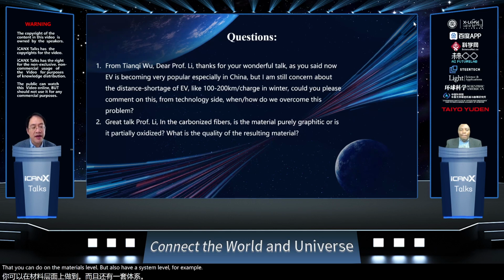So there is a lot that you can do on the materials level, but also at the system level. For example, by inducing so-called internal short circuiting. So by doing rapid preheating with another, let's say, power source, you can basically resolve this kind of problem. And we are already working on this active control, which is you really control the temperature actively, intelligently, rather than taking temperature as a passive variable.